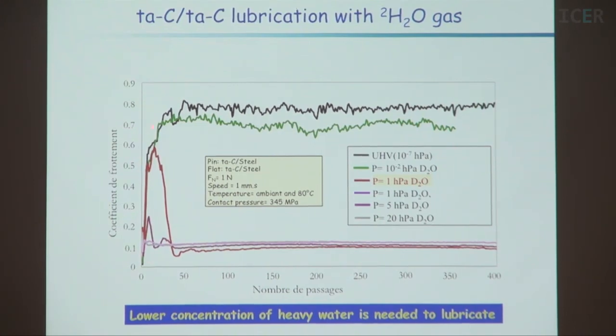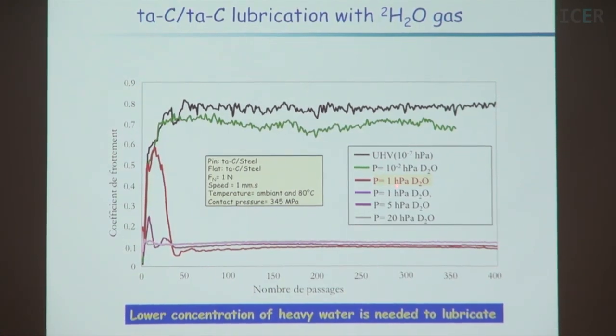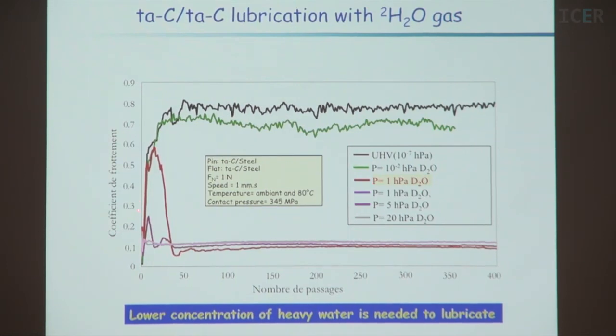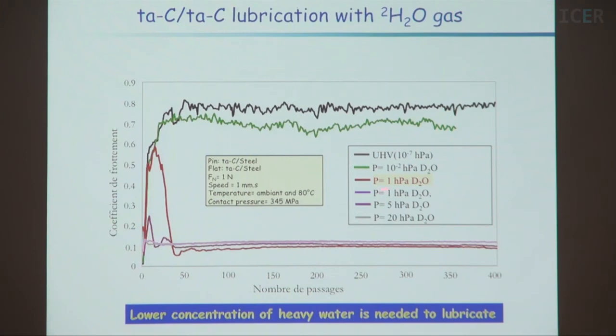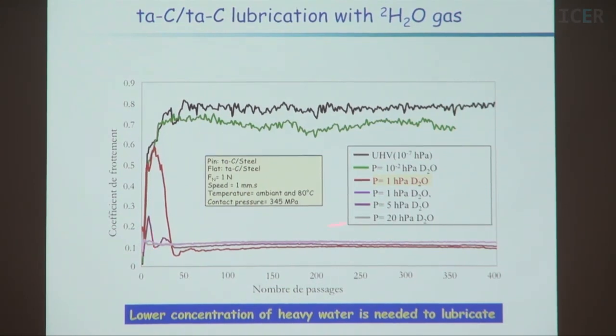So friction in high vacuum, here. High vacuum, very high. We introduced 10^-2 hectopascal, very, very small pressure, in green. Practically no effect. We introduce 1 hectopascal, in red. So you can see what happens. Same story. We produce the dangling bonds, and water reacts with the surface and gives very stable low friction. And if you increase the quantity of water, you keep this low friction. So again, there is a reaction of water with the carbon, which produces the low friction.